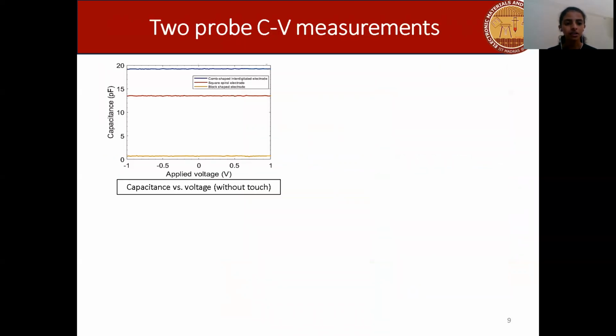Here, we can observe that even though the capacitance values are showing a trend similar to what we have observed, that is, the comb-like structure is showing a better sensitivity compared to square, spiral, or block-shaped electrodes, the capacitance ranges are quite different from those obtained using simulations. Then we can give many reasons for this. For example, the first one, the material that we have chosen in simulations is silver, while in this case, the material that we have used is silver nanoparticles.